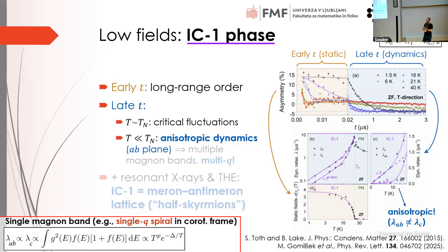The idea there is basically you have just one bosonic degree of freedom at the bottom of the magnon band, which is the only thing that the muon is sensing. It's sensing very low frequency excitations, nothing higher. And this one dominant point contributes the same, up to a prefactor, to both relaxation rates, to both correlation times, meaning that we should see something isotropic, but we don't.